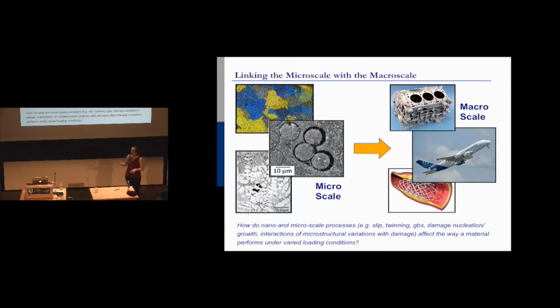So we've been working on that and looking at statistical ways to basically lay out this composite architecture in order to have good cracking and not, I just blew apart my entire component cracking. So things like that. And that work actually is done at, we like to do things in our microscope at kind of unusual conditions. That's actually done at 800 degrees C. You get some interesting things that happen in CMCs at that temperature. So we're doing kind of high temperature loading.